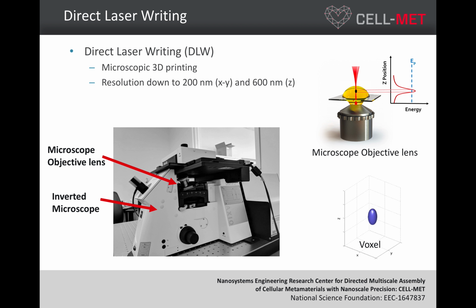We're using a system called a nanoscribe, which is a type of direct laser writing printer. And there's an image of it here. You can see it's an inverted Zeiss microscope, and you can see in the center region, it's kind of dark in there, but you have a microscope objective lens, which gets focused up into your droplet of photoresist, and that's where the reaction happens. And we can get resolutions down to about 200 nanometers in the XY plane and 600 nanometers in the Z plane.